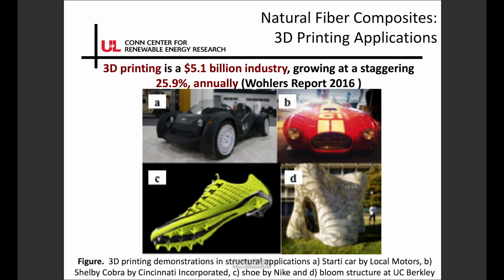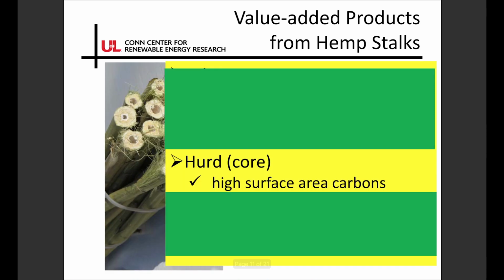The second area is the hurd. The way we are doing the selective hydrolysis, you have seen the composition that hurd has a very high level of ash. Ash is basically going to lead to impurity in the carbons. The acid process that we use removes the ash, making it a low ash starting material for carbons. And by the way we make the process, if we don't go through our process and make carbons,